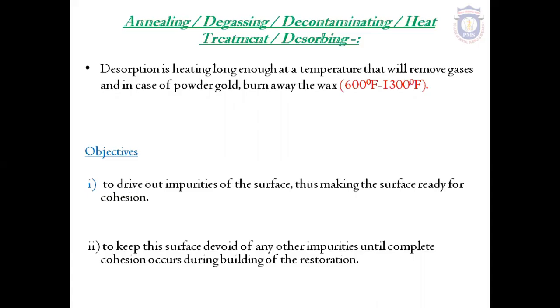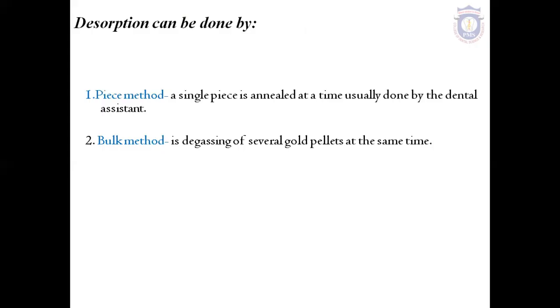So desorption is a process by which heat is applied in order to drive away the adsorbed impurities, or in case of powdered gold, to burn away the wax. The temperature used is 600 to 1300 degrees Fahrenheit. The objective is to drive out the impurities of the surface, to keep the surface devoid of any other impurities until the complete cohesion occurs during building of the restoration. The desorption can be done by either piece method or bulk method. Piece method means a single piece is annealed at a time, which is usually done by the dental assistant. And the bulk method is degassing of several gold pellets at the same time.